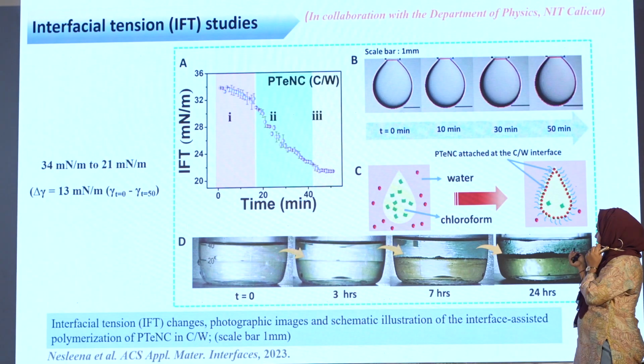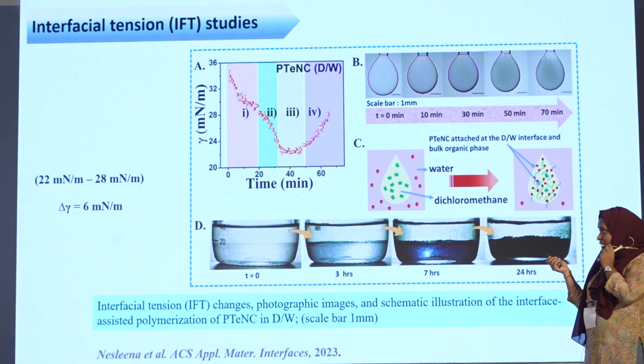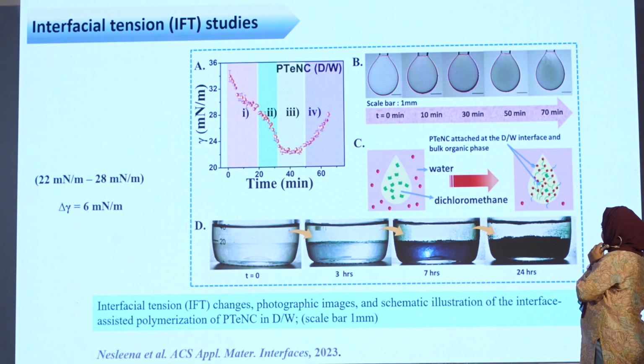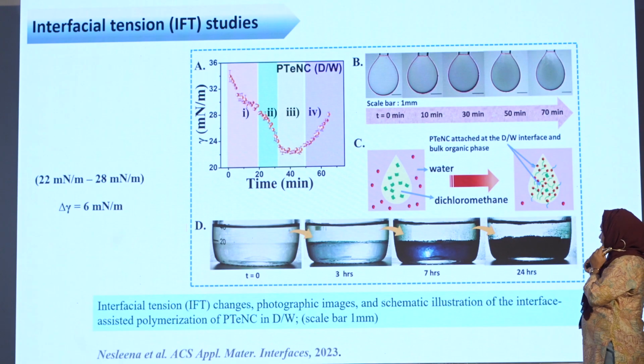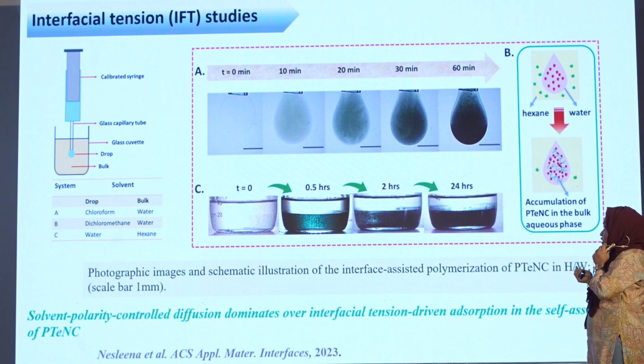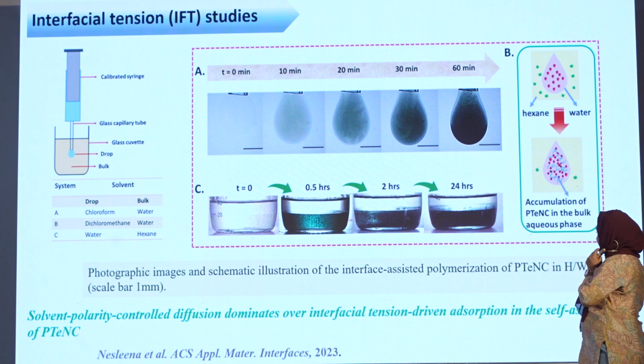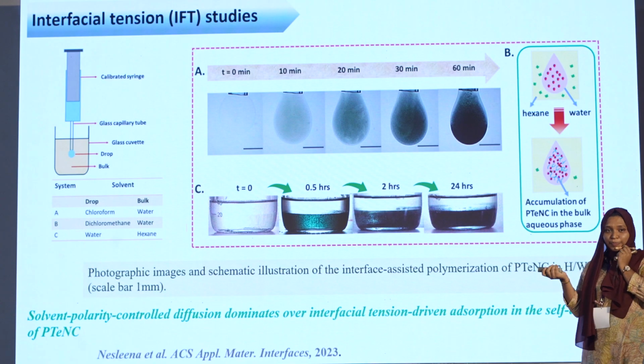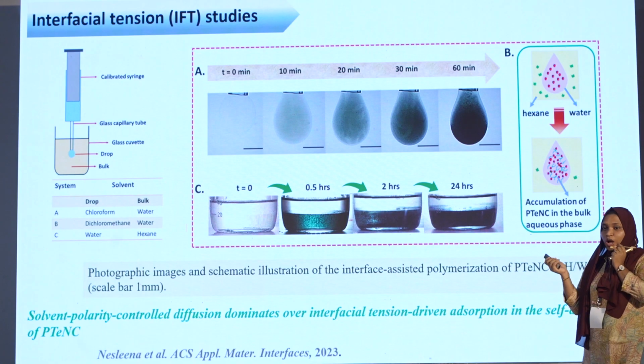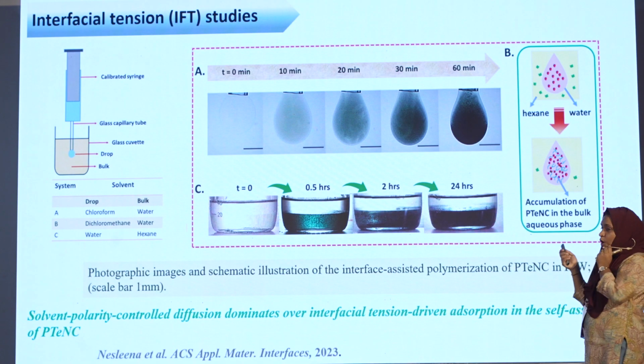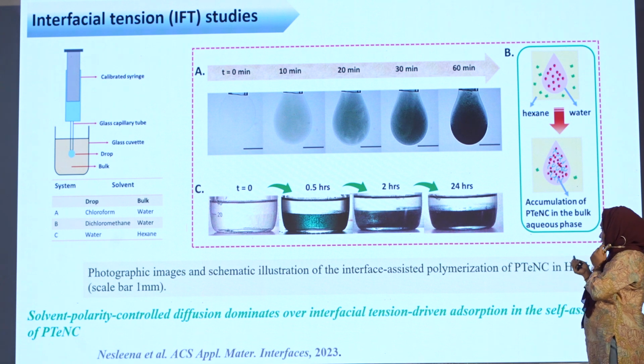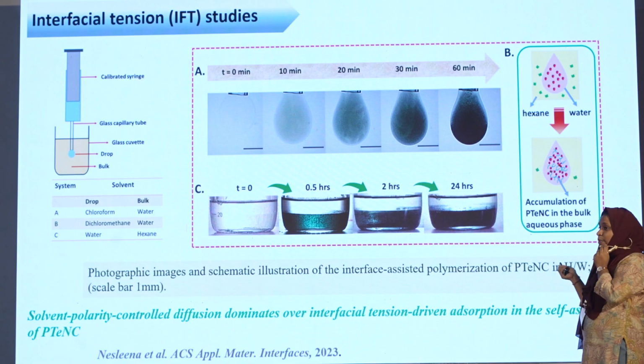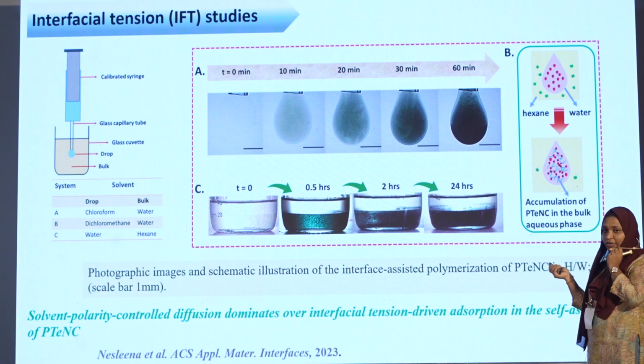Thank you. With the obtained results from pendant drop tensiometry, this is for the DCM-water system, where an initial stabilization indicating interface confinement and then a gradual increase in interfacial tension indicating bulk movement was obtained, and the corresponding optical images captured during the reaction are also given. But in the case of the hexane-water system, since there is a meager difference in refractive index between water and hexane, there was a practical difficulty in checking the IFT. However, we have observed from the pendant drop studies that only bulk aqueous confinement is there for the hexane-water system. Here, solvent polarity controlled diffusion dominates over interfacial tension driven adsorption in the self-assembly process.